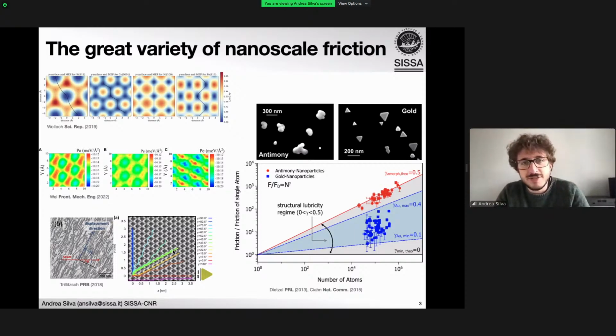At this small scale, the effect of finite size is also very important, as it was shown in 2013 by Dietzel. When you study the friction as a function of size, you see that the friction scales according to specific rules, and in particular, structural lubricity, where the friction disappears in an infinite contact, is shown to display a sublinear scaling with the number of atoms. So the realm of sliding friction at the nanoscale is complex, and even to explore it, we need some guidance.